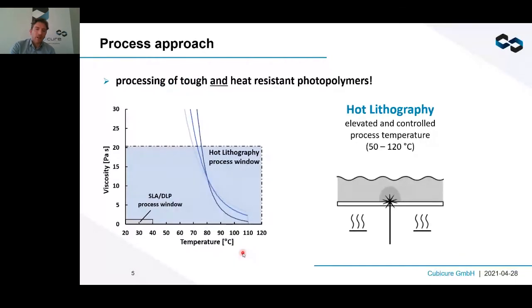First of all, going a little bit into detail about the hot lithography, it's very important to understand that the classical photolithography processes are very limited in their process window. So we have here a diagram which shows the viscosity of a photoresin over the temperature where you use it in the printer. And this small gray box you see here on the left side is a typical process window of a standard SLA or DLP machine. But it would be way more interesting to use other chemicals, which to process them, you need a way bigger process window. We indicated it here with a big blue process window, and that's exactly the process window we opened up with the hot lithography process.